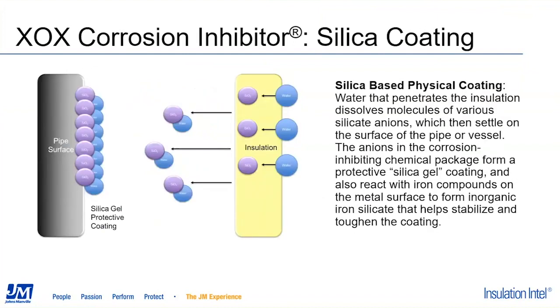The second level of protection that the XOX corrosion inhibitor provides is by creating a protective coating on the surface of the pipe or equipment that has been insulated. So if you do get water penetrating the insulation system, as it penetrates the insulation material, it's going to dissolve those molecules of the different silicate ions that are in it, and it's going to carry those silicate ions to the surface of the pipe or vessel. Those ions are going to then react with the surface of the metal and form a protective silica gel or coating. It's not a coating that you can see. It is molecular in thickness, but it is a protective coating that will be there for the rest of the life cycle of that system, and it is going to provide that protective layer on the surface of the metal.